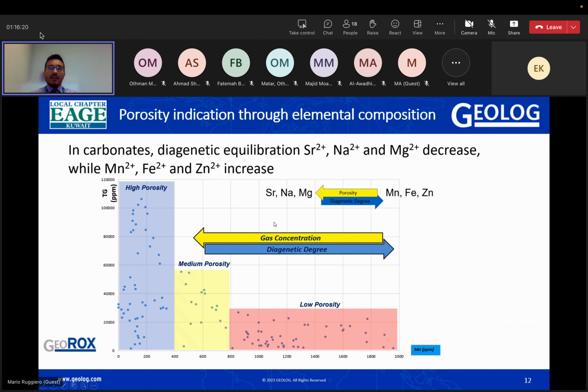Some examples, for example, we have here in carbonates, we can use elemental data as a porosity indication, because in carbonates, during the diagenesis, there is an abundance of certain elements. So manganese, iron, and zinc tend to accumulate with the diagenesis. So you expect to have an inverse correlation with the total gas. And this is really self-explaining in this graph.